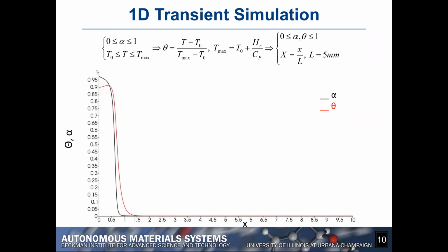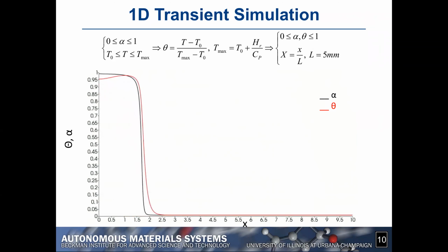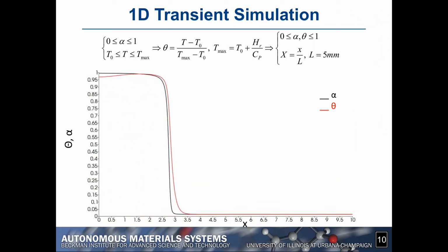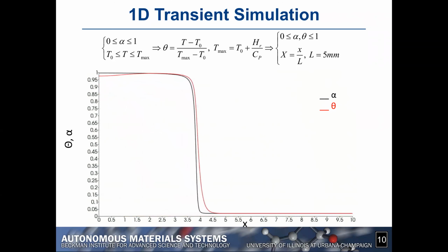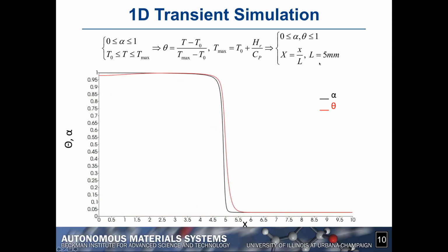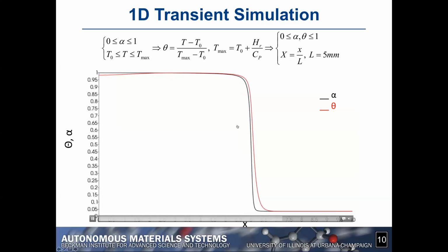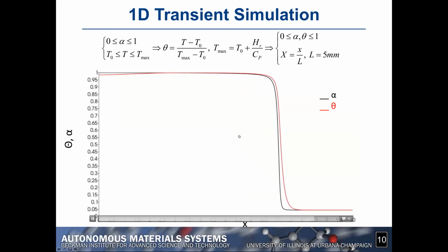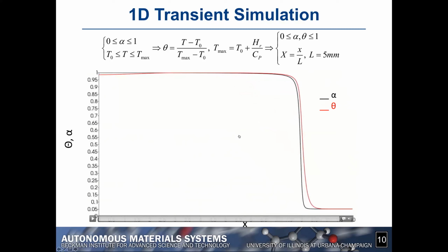And you can see in this animation that after some transients where we start the chemical reaction, the front propagates in a very steady fashion. The first front is obviously the temperature front, followed by alpha. The black curve corresponds to the degree of cure.